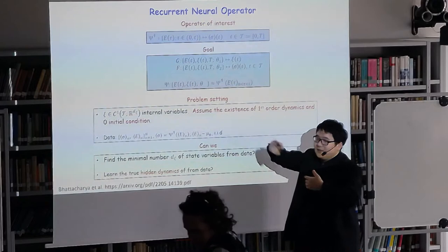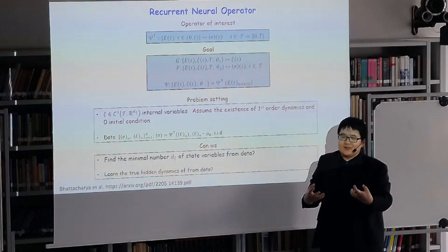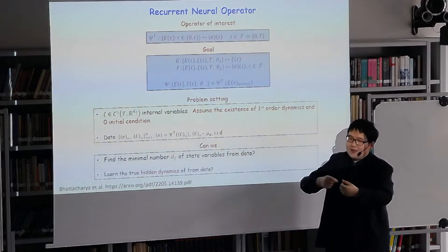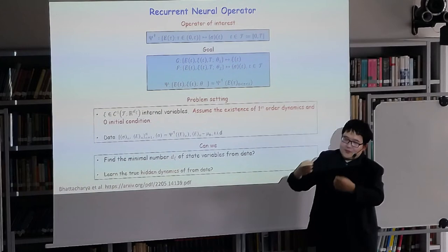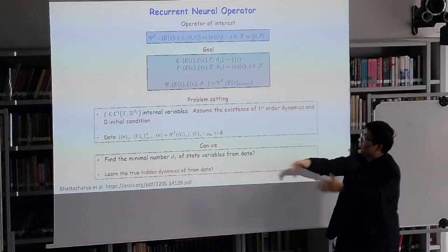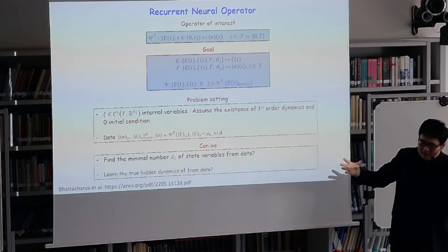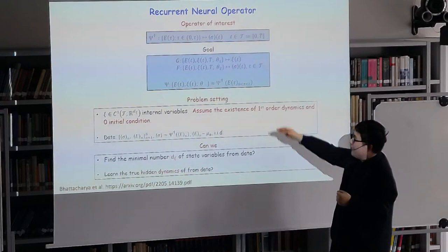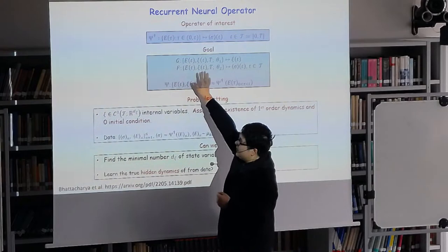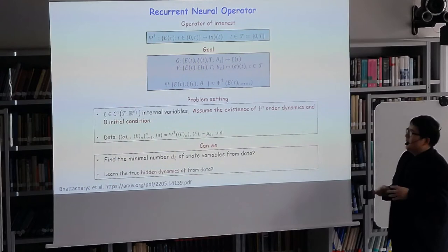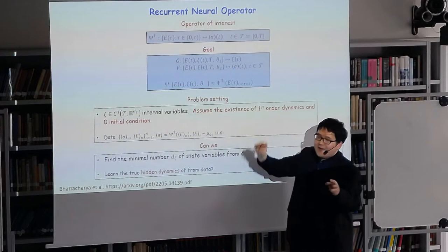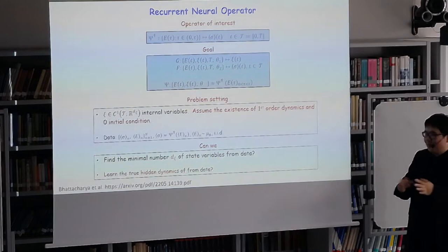And in that regard, that's what I mean by expert judgment. The plastic strain is something that we observed from experiment. We make assumptions on the existence of plastic strains and how they evolve, yield surface and all that. But in this kind of approach, I don't need any of this. All I need is to assume that my micromechanical boundary value problem can be approximated using a finite number of state variables, and there exists an evolution law of the state variables that will give me the approximation of the true map, which can be homogeneous in macro scale, von Mises or something, but we don't have any requirement on that.